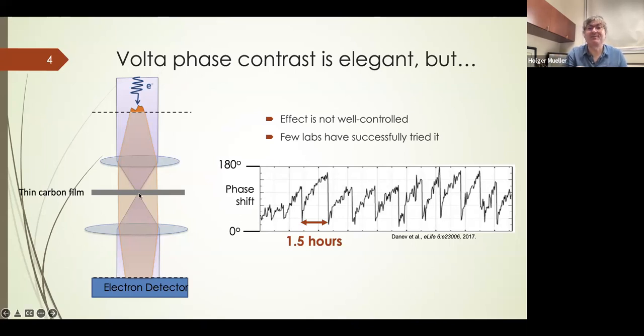Now, the interaction of the electron beam with the carbon film locally alters the properties of the carbon film, and those alterations produce the 90-degree phase shift. Unfortunately, the phase shift is 90 degrees only sometimes, and most of the time it's not 90 degrees. Here you see a plot of the phase shift caused in an experiment, and you see it starts at 0, then the phase shift builds up as the electron beam starts to interact with the carbon, reaches 90 degrees, and soon exceeds it greatly. And then you have to find a new spot on the Volta phase plate, and the process starts again. So what you can see is, while the effect leads to glorious images sometimes, it is not well controlled, and therefore few labs have successfully used it for cryo-EM reconstruction.